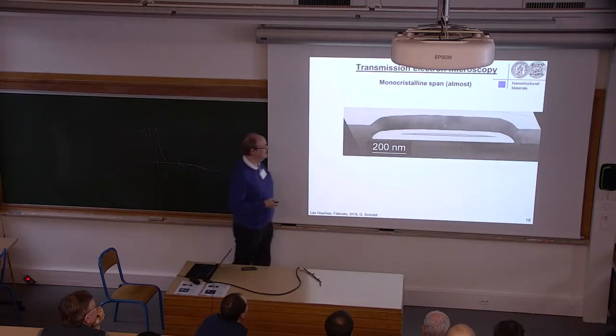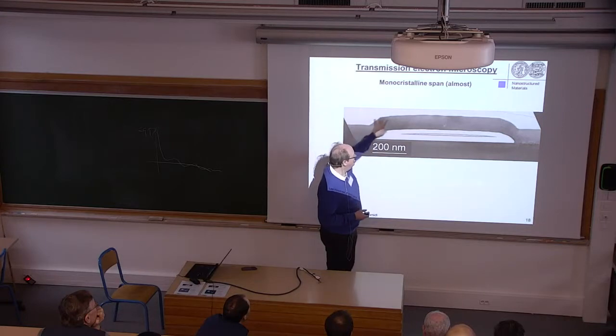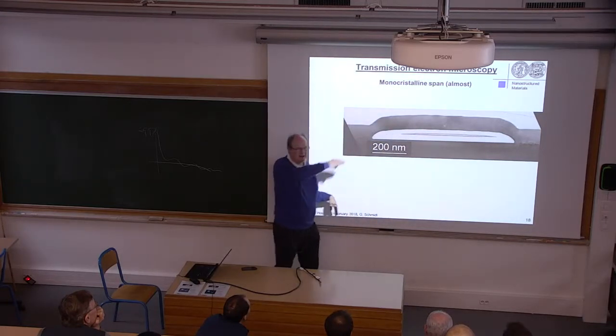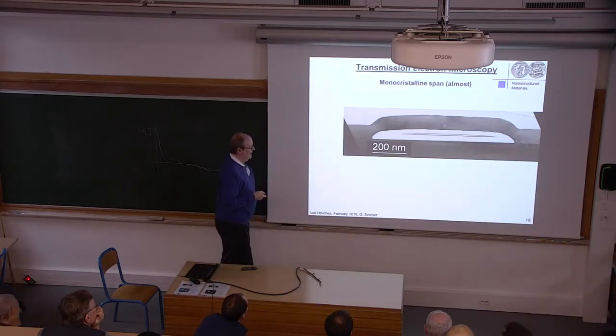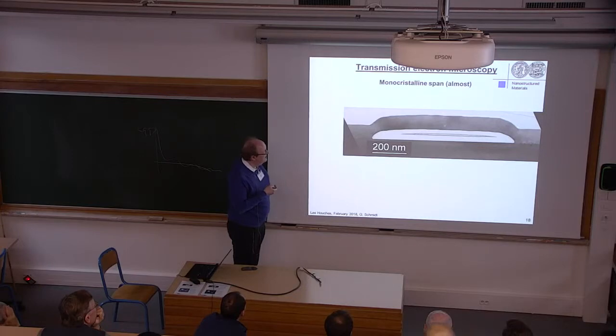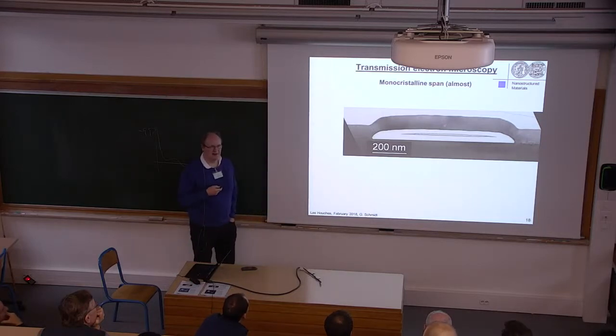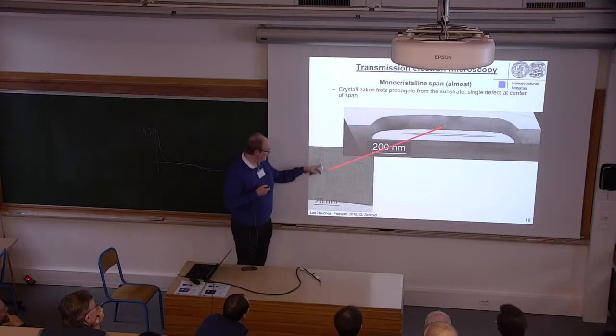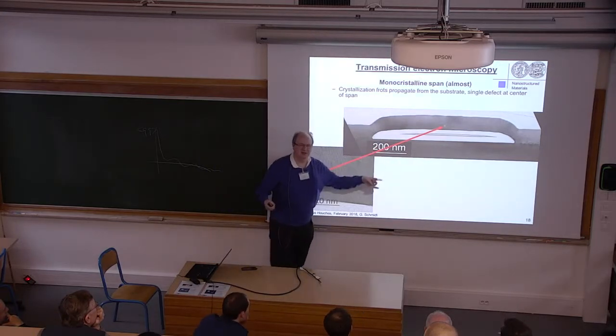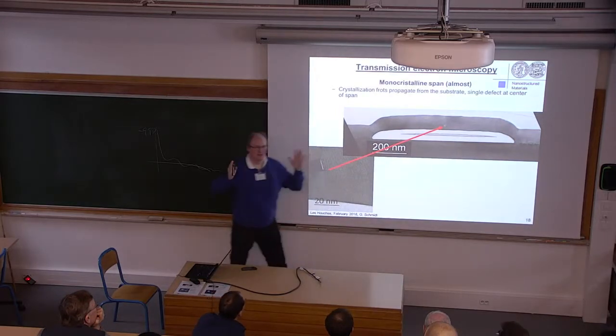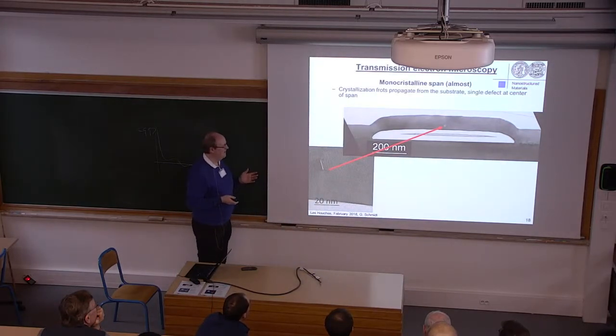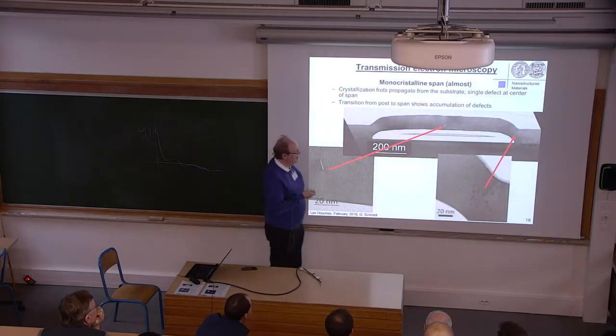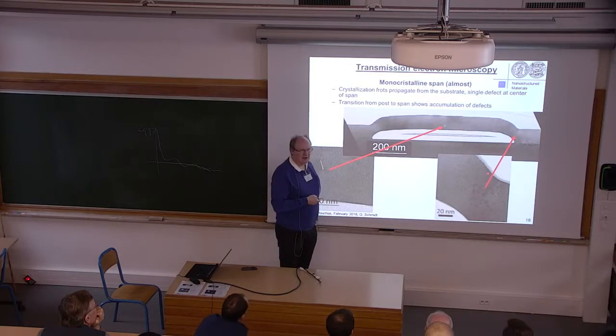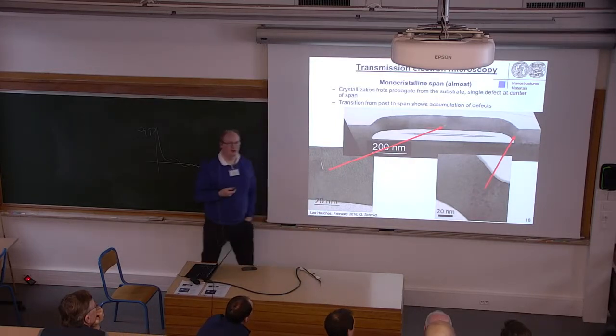This is how they look from the inside. This is a cut through a bridge, and you can see it's pretty straight. At least you don't see this banding, which seemed to be there in the first picture. You cannot see here that the thing is really crystalline. However, I can tell you already that the span is almost monocrystalline. This is in the center because during the annealing it starts to crystallize from here and from there, and somewhere these crystallization fronts meet in the center and you get a kind of stacking fault there. And also here you have a lot of strain and quite a number of defects. But the span itself is like a monocrystalline slab of YIG.